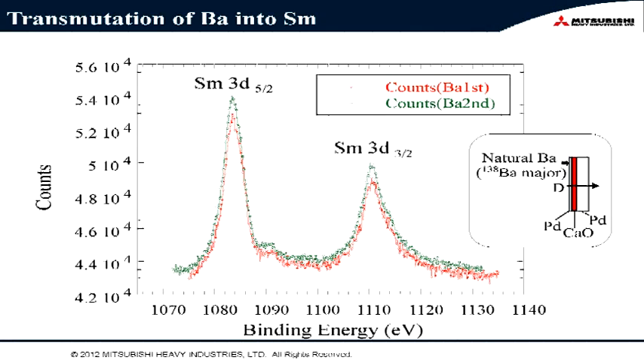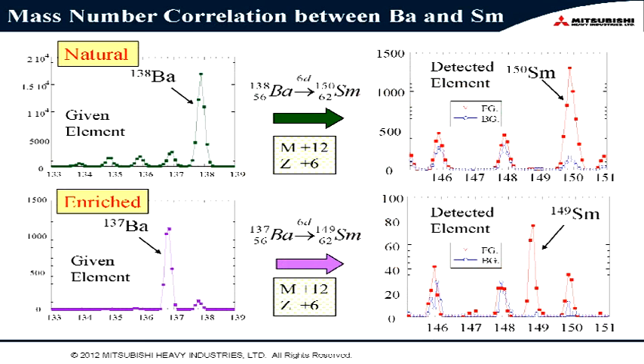In the next experiment, we put barium instead of cesium. In this case, we get samarium. This is the result of XPS analysis. We get a very clear samarium spectrum. And this figure shows the mass number correlation between barium and samarium.